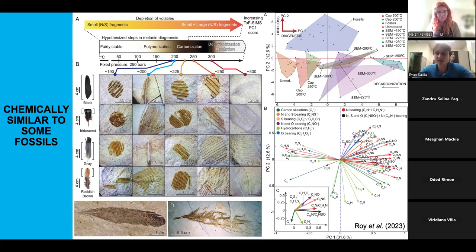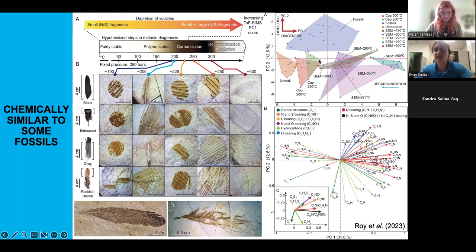So this is work using time of flight secondary ion mass spectrometry, led by Arindam Roy. And what we found is that when you synthetically fossilize, quote unquote, these feathers, not only do they look like genuine fossil feathers, but we appear to be able to simulate a lot of the diagenetic continuum here, where you lose volatile small components and you increase your cross-linking polymerization of this melanin pigment. And so most of the variation, principal component one, is this diagenetic continuum of temperature, and also whether you do it in sediment, which is an open system, or a closed system capsule.